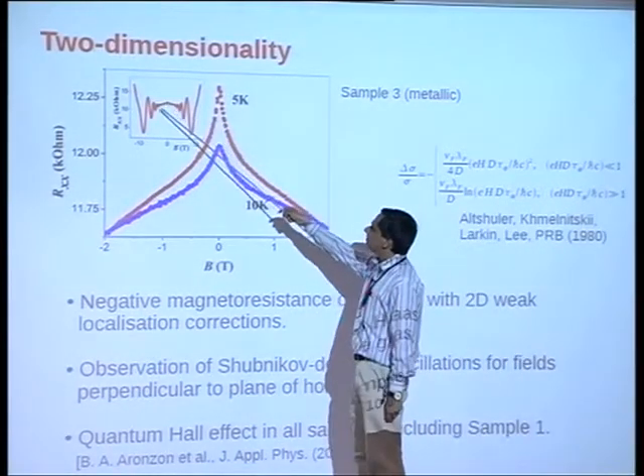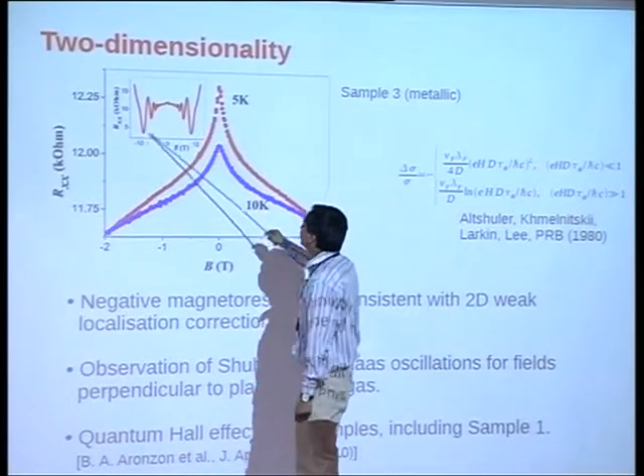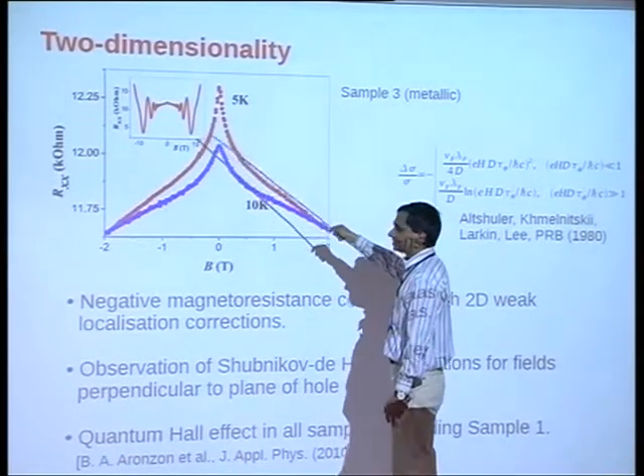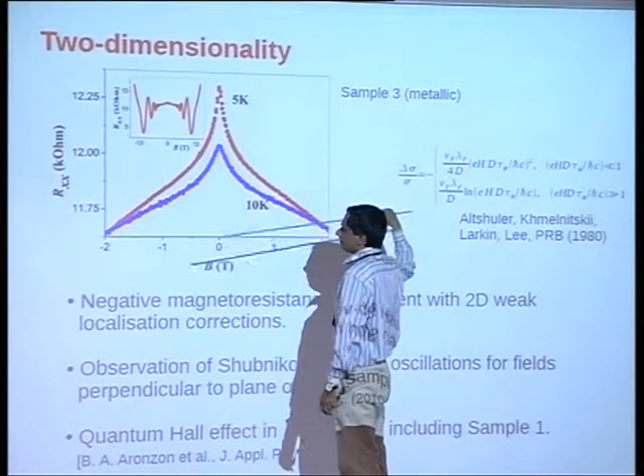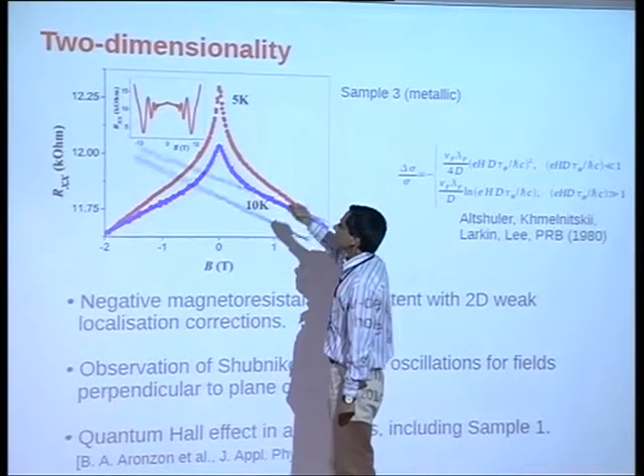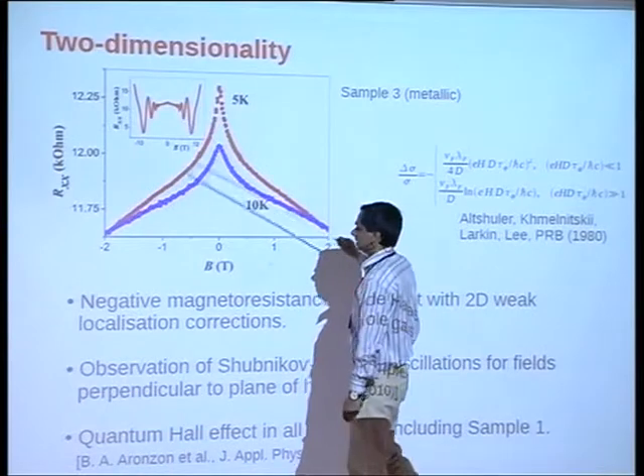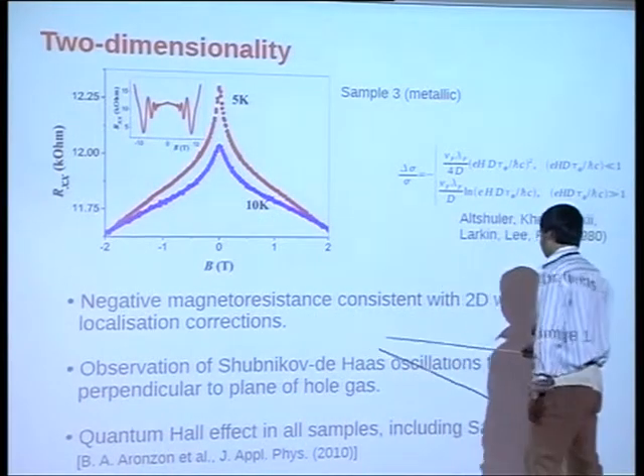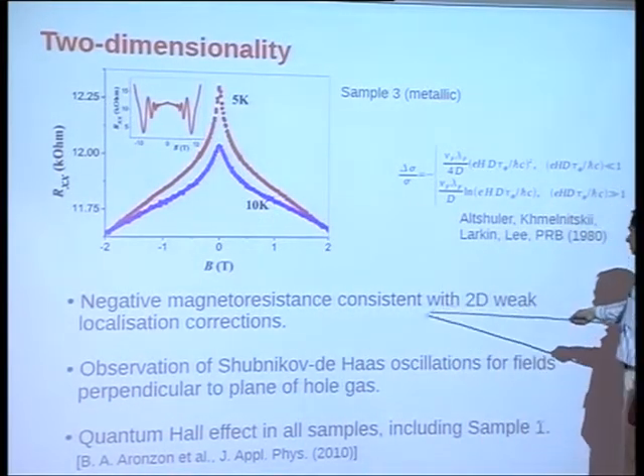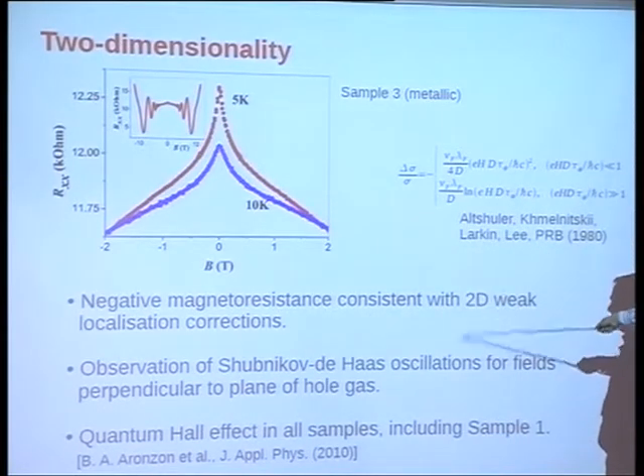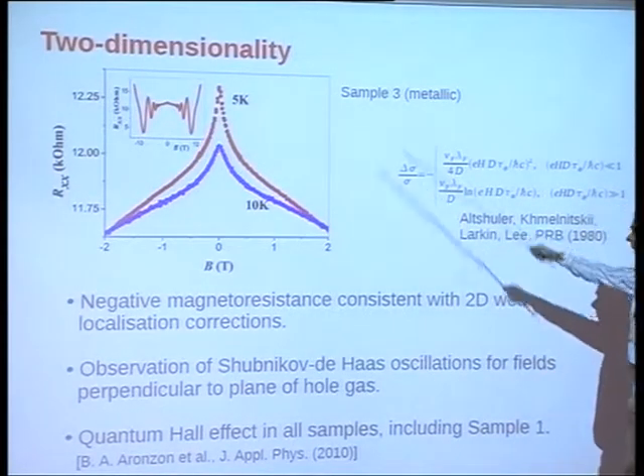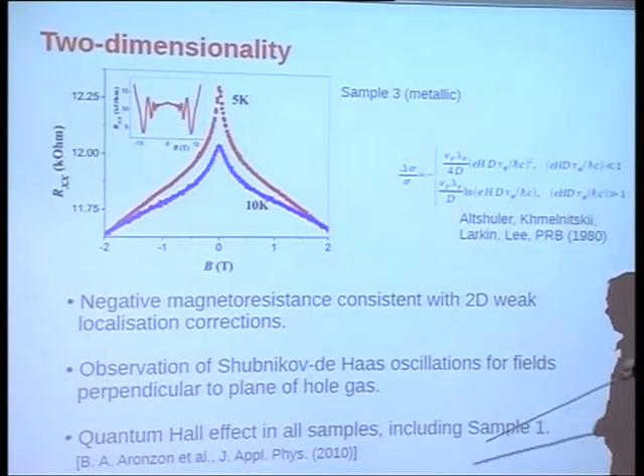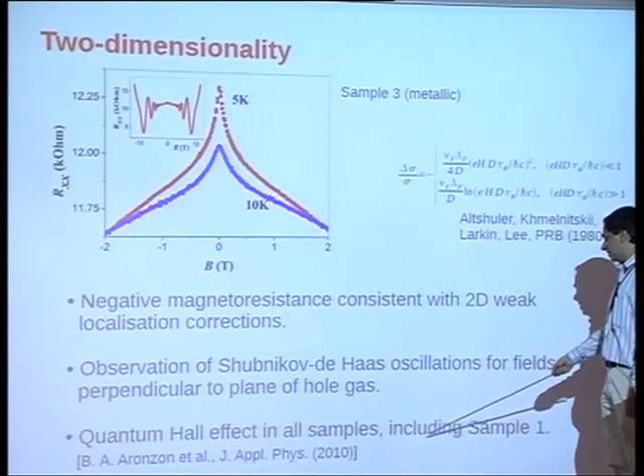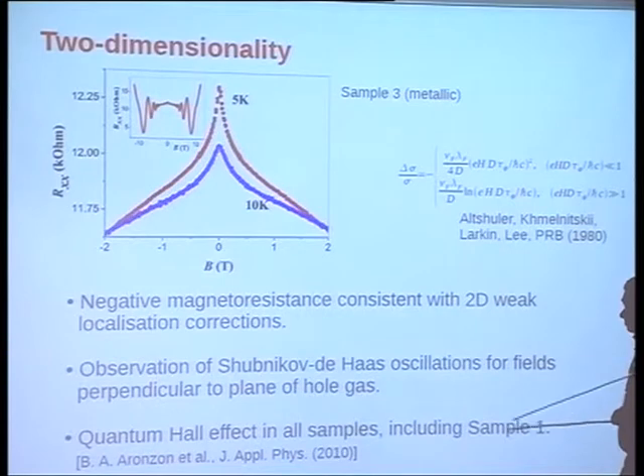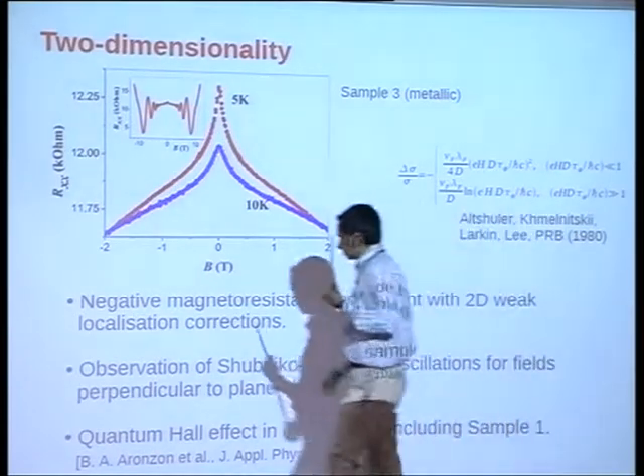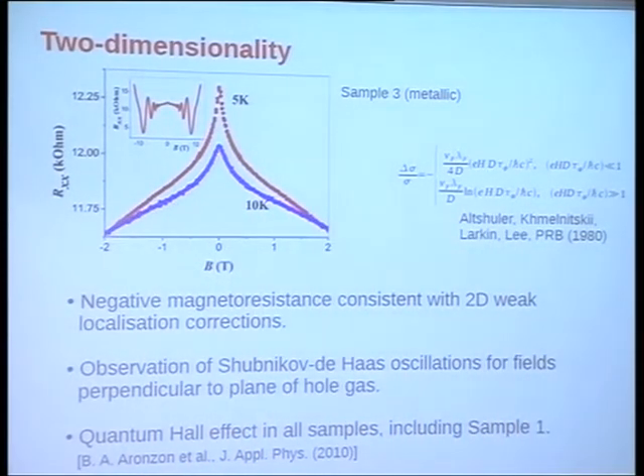You also see Shubnikov-de Haas oscillations as you increase the magnetic field, but you don't see them if you put your magnetic field parallel to the device, which is also evidence of two-dimensionality. So the negative magnetoresistance is consistent with 2D weak localization, and Shubnikov-de Haas also perpendicular to the plane. And finally, quantum Hall effect is seen in all the samples, including the insulating ones. So these devices are indeed two-dimensional.